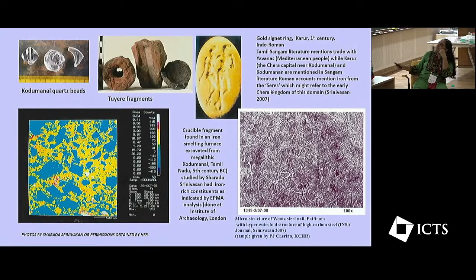And this is in fact a cross-section of the crucible, on which metallography was done, and then looking at other techniques, here what was used is scanning electron microscopy with electron probe microanalysis. And this is a dot matrix map where basically you can map the concentration of elements across the surface. And this shows the enrichment that you see here, the iron in the crucible matrix. So you can tell that this was actually used for crucible processing of iron. So this is how the analytical techniques can be used to tell us something.